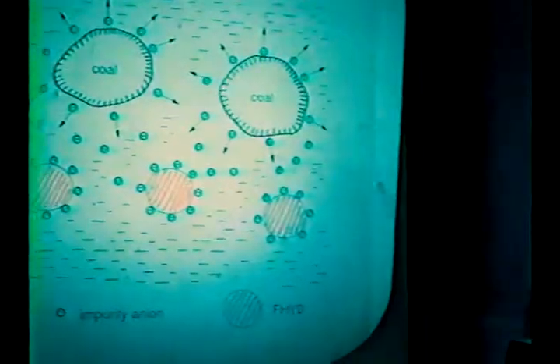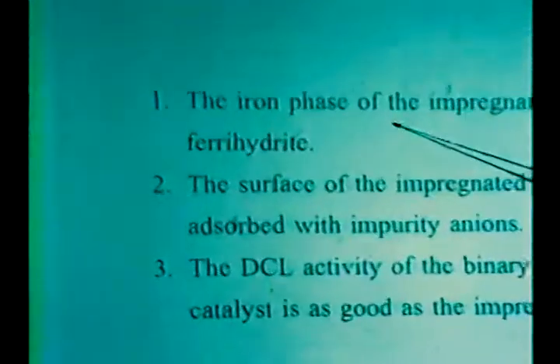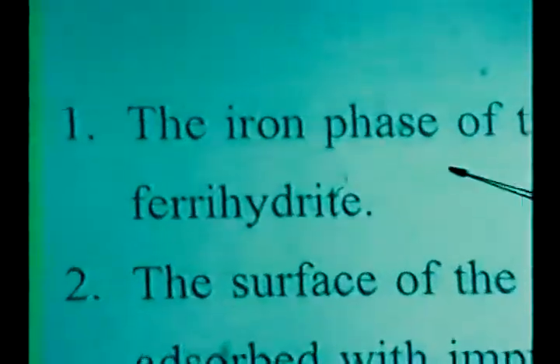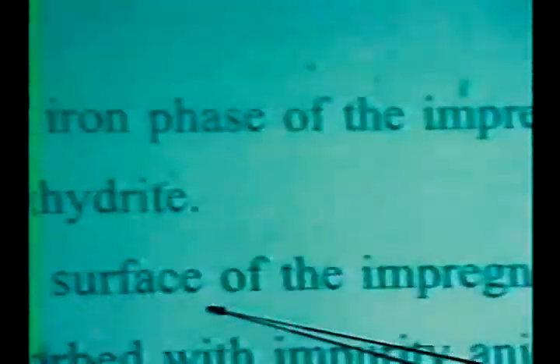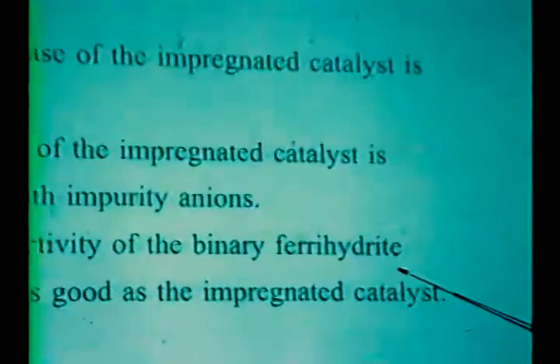Probably it is the case, but to convince you, this is not enough. We need physical evidence. First, we have to prove the iron phase formed indeed is ferrihydrite. Secondly, we have to prove the surface is different, that the surface is adsorbed with impurity ions - we have to have physical proof of that. Also, we should prove the DCL activity of this binary ferrihydrite catalyst material is as good as the impregnated catalyst.